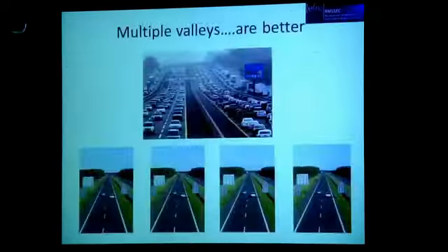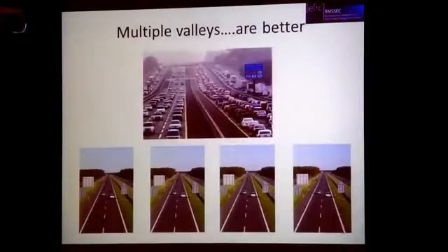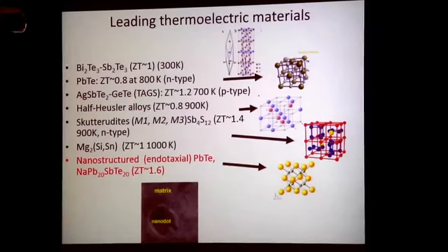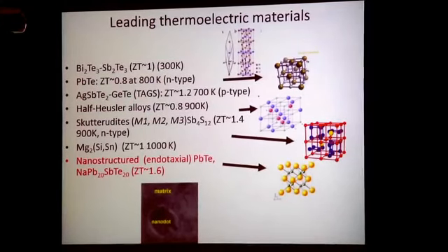So, first of all, it means that we're looking for such materials. So what are the leading materials today? There's a number of them. I start from the top, sort of the oldest material, bismuth telluride, antimony telluride, ZT of 1 at room temperature. This is still the best material at room temperature. Lead telluride, about 0.8 to 1 at high temperature. This is an old material. This TAGS material was the first, one of the oldest materials that had ZT over 1, because 1 was thought to be some sort of a barrier for a long time.